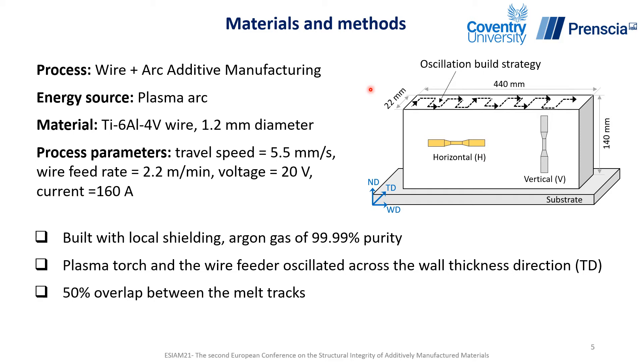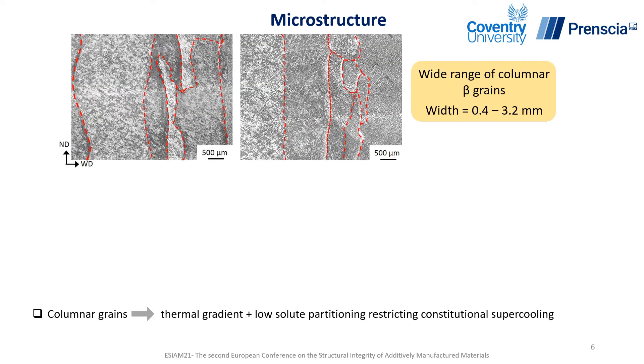The entire wall was built with local shielding of argon gas. During the deposition we used an oscillation build strategy developed for WAAM, where the plasma torch and the wire feeder were oscillated across the wall thickness direction with a 50% overlap between the melt tracks. The microstructure features observed in WAAM Ti-64 are similar to what we have seen in other AM processes. The steep thermal gradient and low solute partitioning of Ti-64 alloy restrict constitutional supercooling, resulting in columnar grains aligned along the build direction; however, in some cases we have also observed some near-equiaxed primary beta grains.